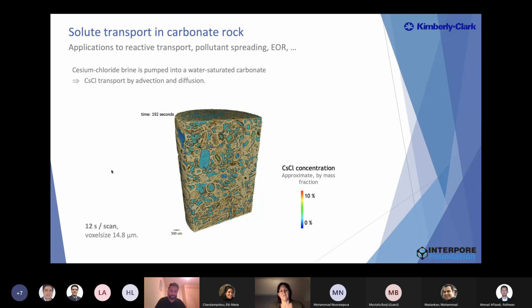We are scanning very fast, and you can follow in function of time which pores are being slowly filled with the cesium chloride, moving from the bottom through the sample. You see how the concentration is changing over time.